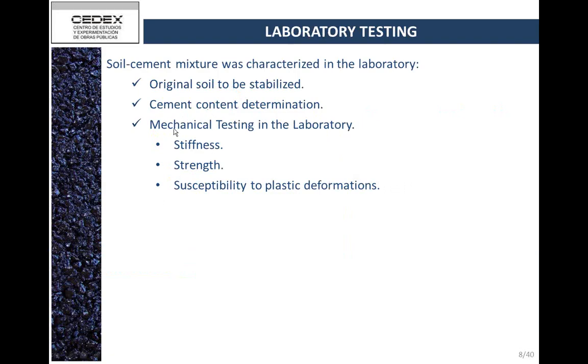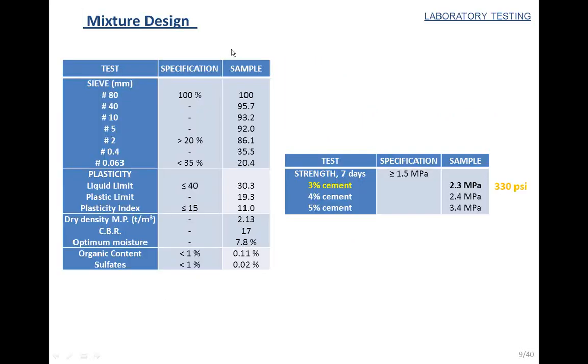First of all, we did the testing of the soil that we were using for the stabilization. You can see here the specification of the Spanish normative, and then you can see here the results that we obtained for a specific soil. You can see that we require the amount of filler to be below 35%, and here we have 20%, and we require the liquid limit to be below 40 and the plasticity index to be below 15, and well, this soil was not very bad, so this soil was able to fulfill this requirement. You can see here the requirement for the organic content and for the sulfates.